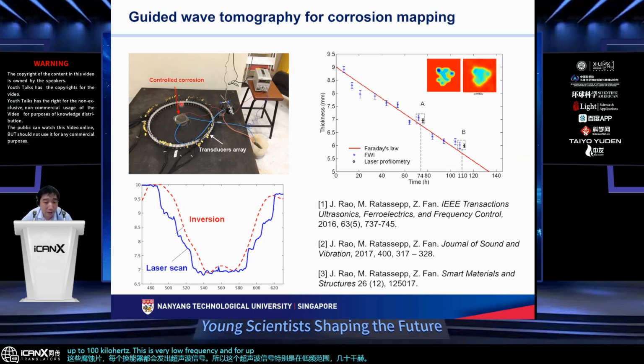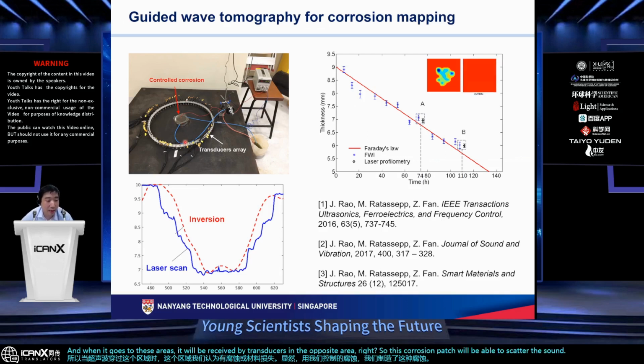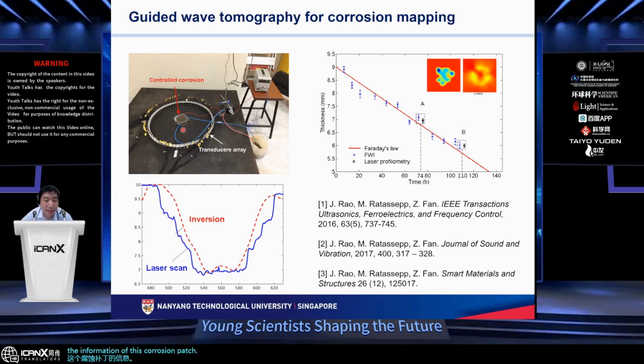For ultrasonic guided waves, the velocity changes with the frequency-thickness product. So when the ultrasound goes through an area where there's corrosion or material loss, which we manufactured ourselves, it will be received by transducers on the opposite side, right? This corrosion patch scatters the sound, and the scattered sound carries the information of the corrosion patch. Then, using inversion algorithms, we are able to reconstruct the velocity map around this region, and from the velocity map, we are able to get the thickness map. So this is the general idea.